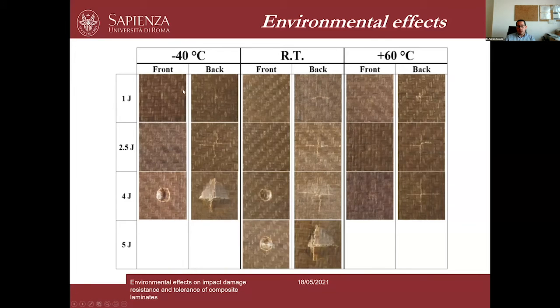These are the resulting damage modes on the front and back surfaces for the different levels of impact energy at the different temperatures. For example, if we look at what happens at 4 joules, we can easily see that when we move from -40 up to +60 degrees Celsius, the damage on the front face is completely different, and it is hardly detectable at +60 degrees Celsius. This means that at this temperature, the composite became much more compliant. On the back surfaces, we didn't detect a significant change in the damage modes because there is always the presence of these cross-shaped micro cracks.